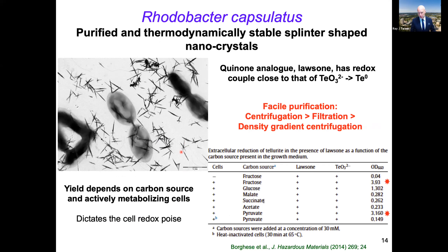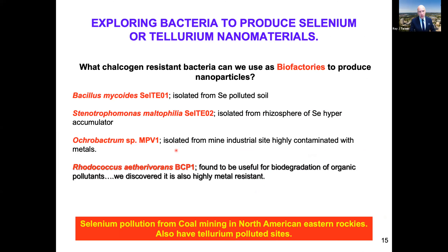This work began around 2014 when we were working with a photosynthetic bacteria. We were able to make tellurium nanorods quite effectively by playing with the physiology — essentially giving the bacteria different food sources to generate a unique physiological state. We also added an electron conduit molecule, lawsone, and were able to get higher yields of the nanomaterial, producing rods approximately 50 to 250 nanometers in length.